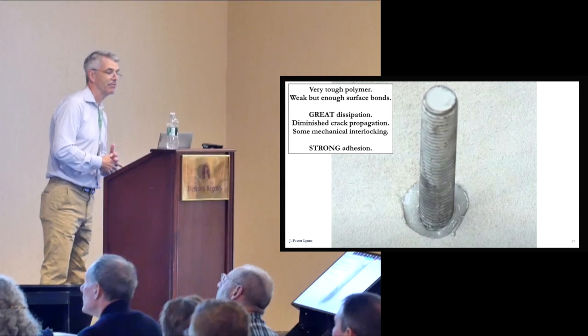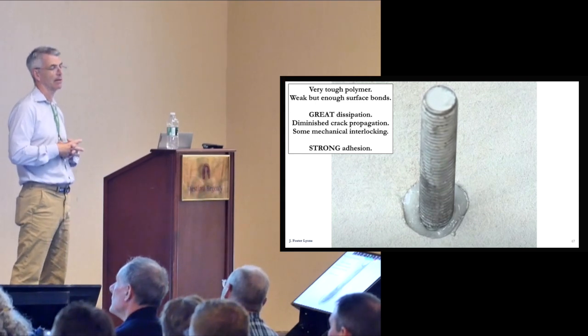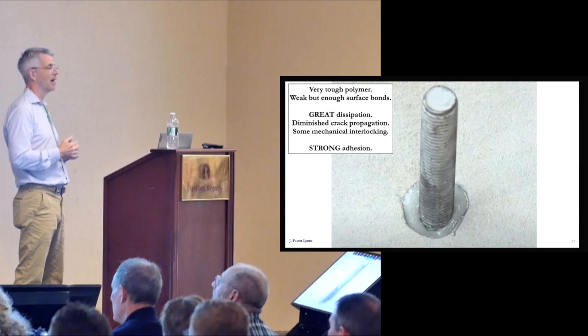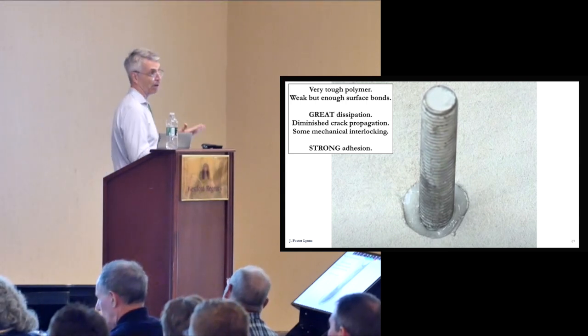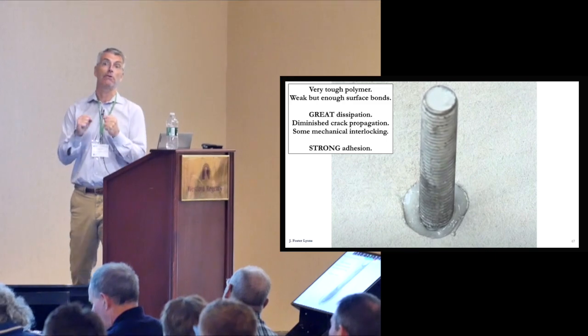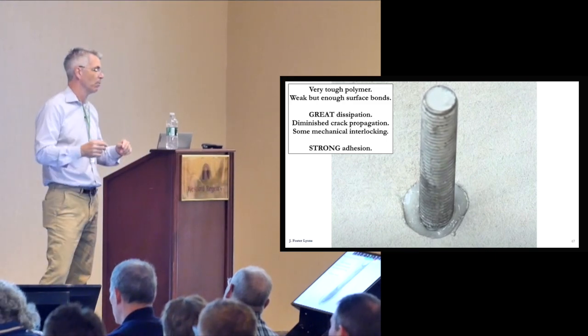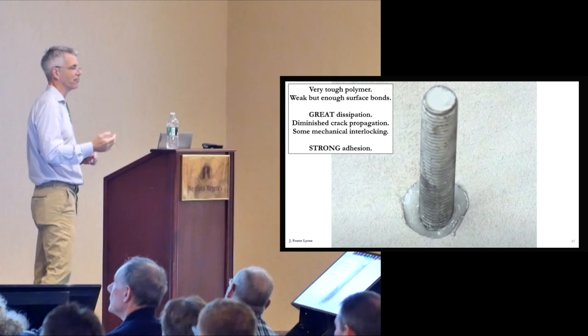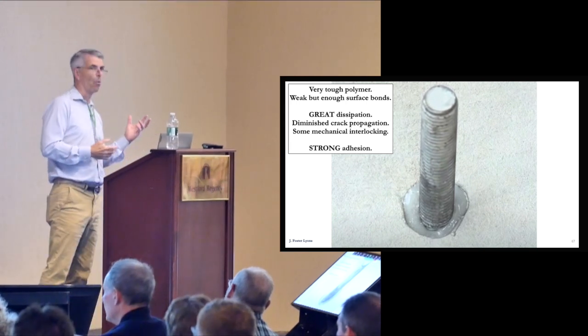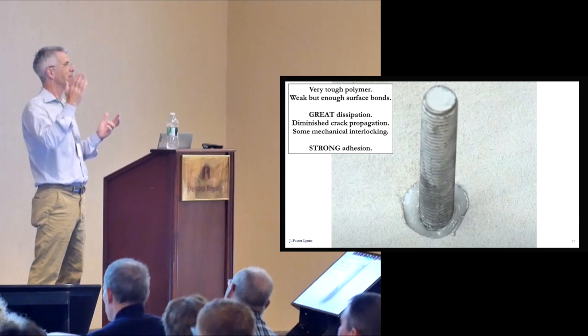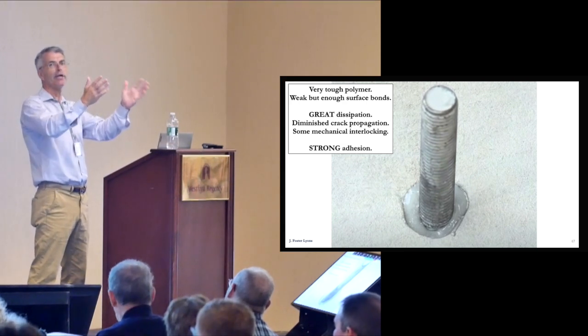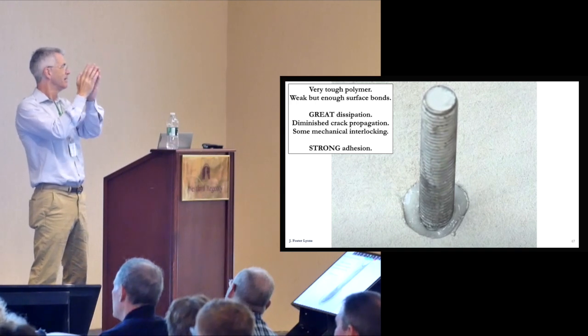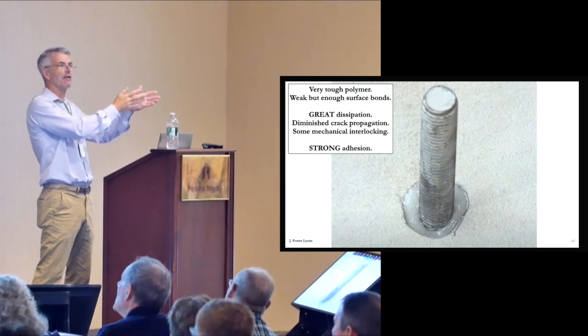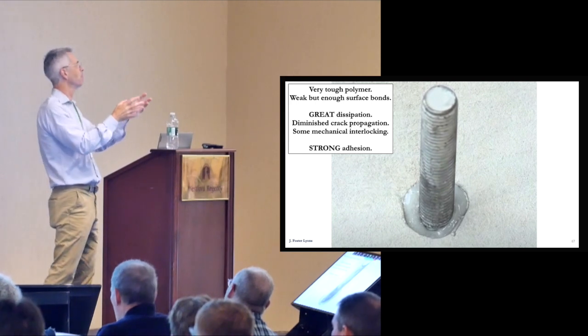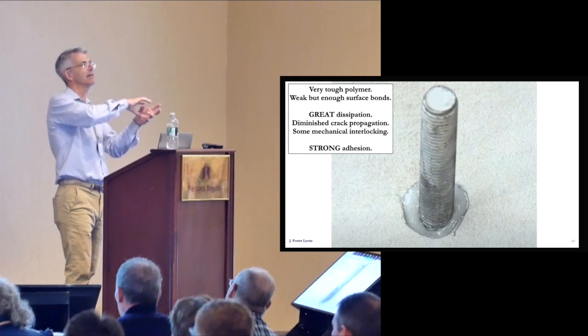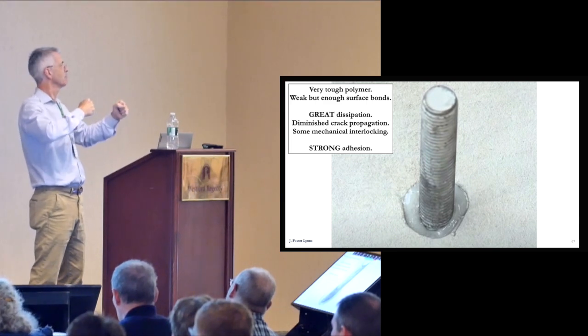All right? This is an epoxy adhesive on a bolt in some concrete. Structural epoxy adhesives are actually very tough polymers. They're tough, for lack of a better word, right? They're not like crappy, weak bubblegum polymers. And again, weak surface energy bonds. The bond between the epoxy and the metal is a weak surface adhesion bond, and the bond between the epoxy and the concrete is a weak surface energy bond. There's not some super strong chemical bond in there. It's crappy, weak bonds. But the epoxy polymer between them does the work for you.